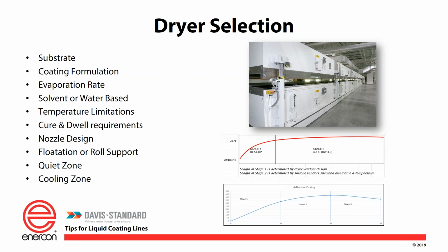Solvents, we need to keep those below a standard level, referred to as LEL or LFL, lower explosion limits or lower flammable limits, to keep it safe. And there we'll balance our recirculations, our temperatures, and our evaporation rates to maintain levels that are safe in the LFL world. Temperature limitations, again, that's mostly going to be your substrates, but there are times where we're going to have coatings that need to have certain temperatures, whereas with the next one here, cure and dwell requirements, they require a very high temperature for a period of time. So there are limitations. Sometimes I need higher temperatures, other times I need lower.